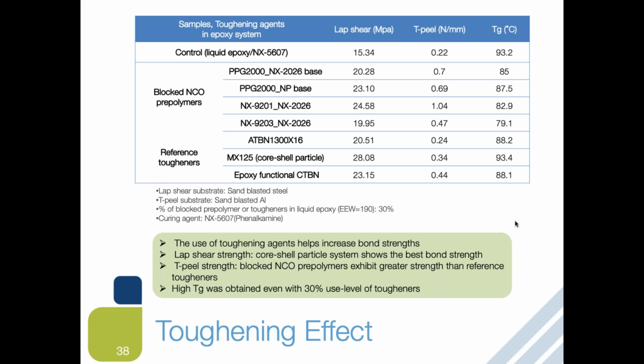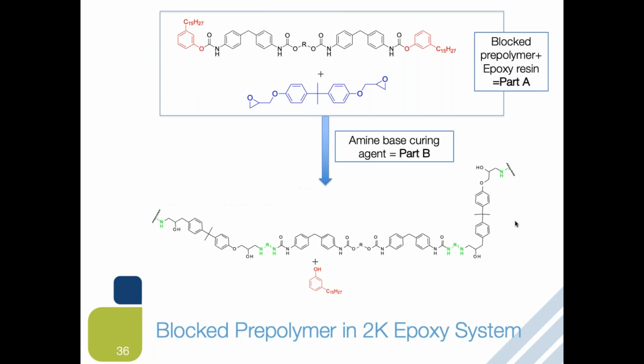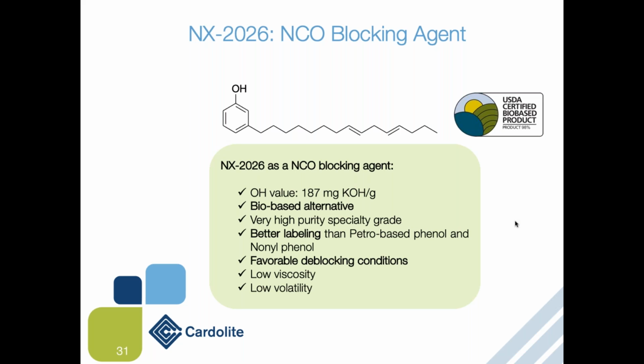Right. In a few slides we mentioned this a little bit. Unlike other renewable feedstocks, for example castor, soybean, and those types of vegetable oil-based feedstocks, cashew nut shell liquid technology, as you can see from this structure, offers one more component, being phenolic, an aromatic structure with a long aliphatic chain. Most vegetable oil-based feedstocks do offer a long aliphatic chain, meaning you will get very good hydrophobicity. However, you do not get this aromatic structure, and aromatic structure typically offers better chemical and thermal performance.